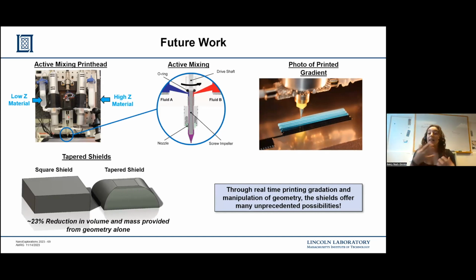Additionally, we want to see how the shield shape affects the radiation blockage. By tapering the shield from a square shield to that nice curved edges, we have a 23% decrease in the volume and mass. So we decrease our SWaP penalty. The added benefit is that radiation isn't a linear phenomenon. It comes from all over in space. So we're curious to see how changing the shape of the shield affects how much radiation we actually block. By adding these two additional degrees of freedom, we are opening ourselves up to so many unprecedented possibilities of what we can do. And in order to best figure out what direction to go to and how to create the best shield possible for a specific mission, we are hoping to create a model to help us do this.